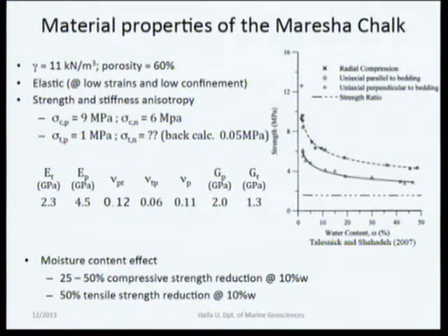The compressive strength depends on the direction, it's anisotropic. It's about 9 megapascals if it's parallel to the bedding planes, and 6 megapascals when it's normal to the bedding planes. And just to give you some kind of reference, the standard concrete is 30 megapascals. So it's about 3 to 5 times weaker than concrete. Also very important is the tensile strength, which in most rocks, also in concrete, is about an order of magnitude and even more lower than its compressive strength.